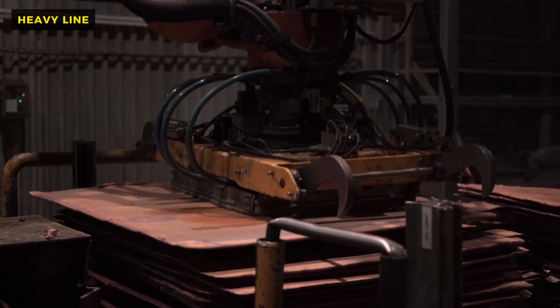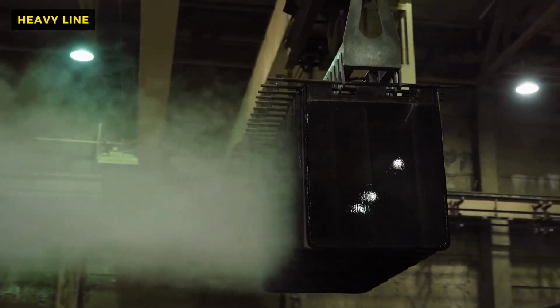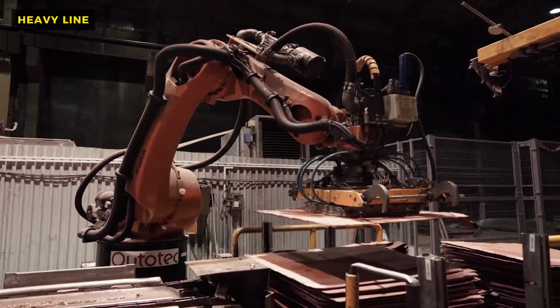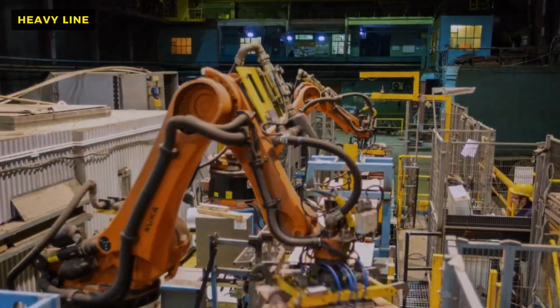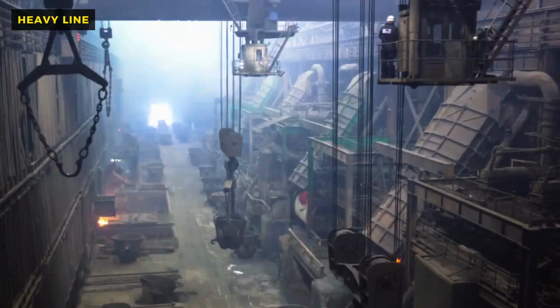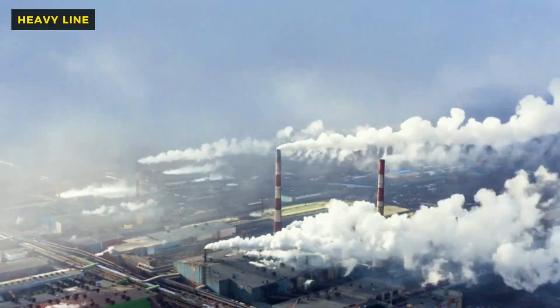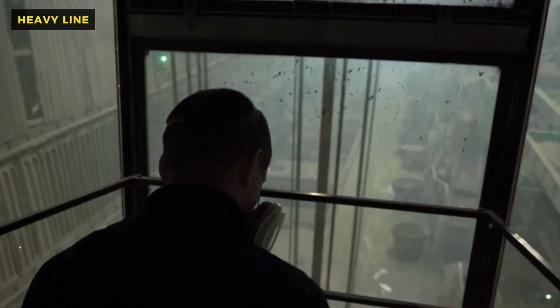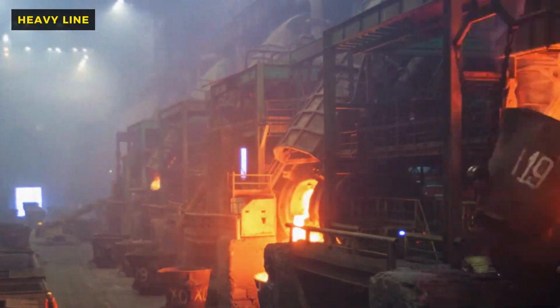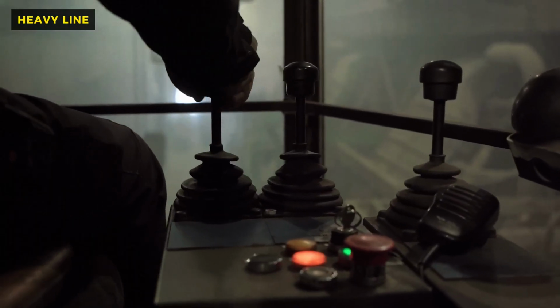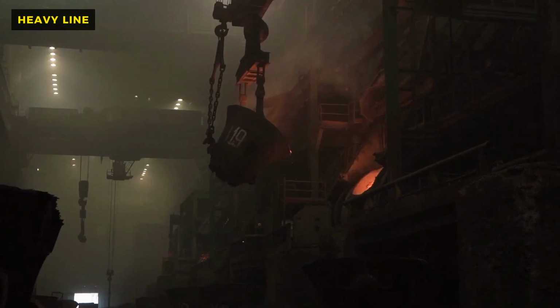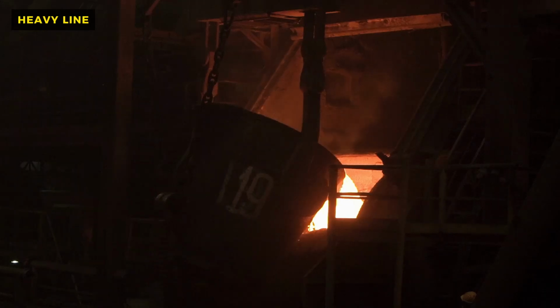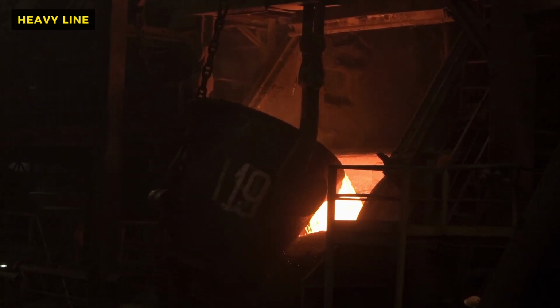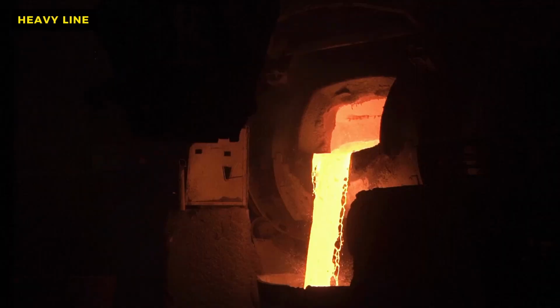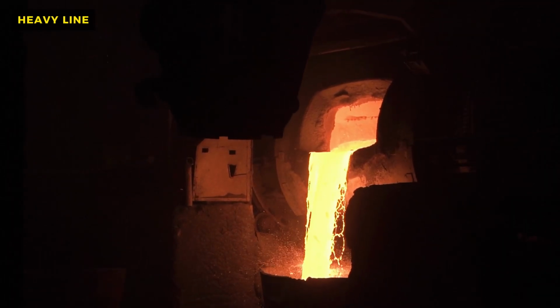The chemicals make the copper sulfide particles water repellent, so they attach themselves to the rising air bubbles, floating to the surface as a metallic froth that looks like shimmering dark gray soap suds. The nickel sulfide, however, remains wet and sinks to the bottom. It is a gravity-defying trick of surface chemistry that allows engineers to separate two metals that are chemically very similar.